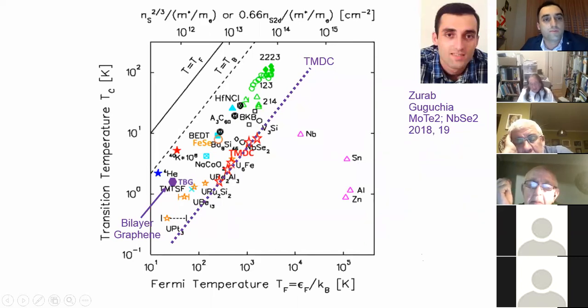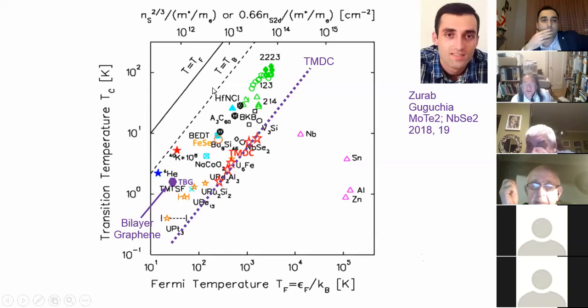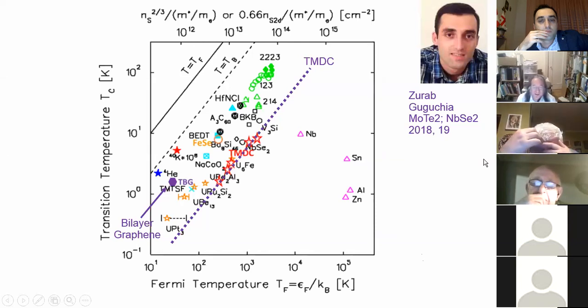Yeah. So actually, I hope to show that the superconductivity is somehow determined by this parameter, number density of carriers divided by the mass. This is one factor. And the second factor is competition with competing ordering state. And so there are a few other ways to try to go to higher transition temperature. But this laser experiment is giving us a very nice indication that at least light is seemingly changing the balance between competing orders.